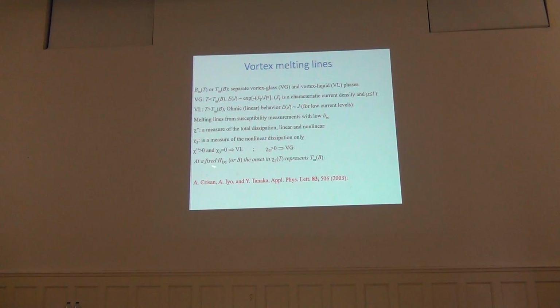So the measurement goes like this. You fix a DC field, and the onset in the temperature dependence of the third harmonic represents actually the melting temperature of the vortex system at that magnetic field. So here are some measurements you see. The difference is that there is a difference in the noise level for the third harmonic compared to the signal from out-of-phase susceptibility. So this is 0.5 Tesla. You see the onset of chi double prime, and here the onset of the third harmonic, and this happens at all magnetic fields we tried, between 0.5 Tesla up to, I think, 9 Tesla here.